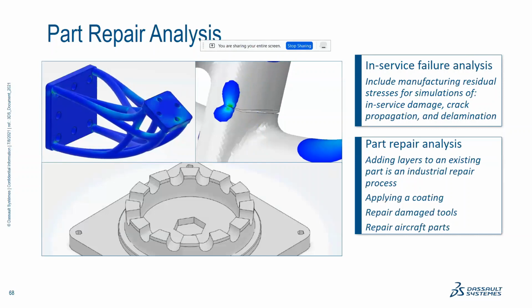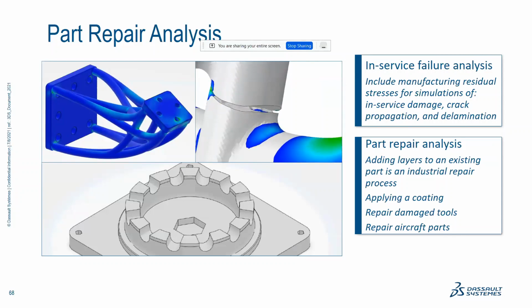One key advantage which we have seen used a lot in the industry is for repair analysis. So you have a certain part. It is not always possible to build a new part. So any part which has been functioning and has any repairs is a limiting factor in the performance. So it can be quickly repaired. We have the legacy design. So if any repair strategy is to be evaluated, we can virtually simulate it. Say in case of a welding process or any part which is to be added, then we can simulate, say, the laser welding motion in this repair analysis, and then find out what is the best way to ensure that the part repair is satisfactory and is able to meet the subsequent post-failure criteria in terms of part performance.